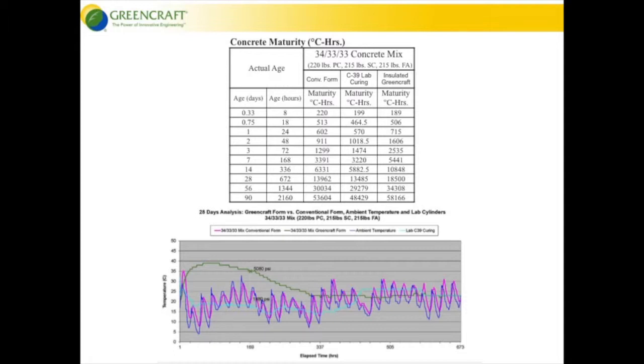Let alone stripping, reshoring, let alone the forms. Same thing, cored at 5 days, broken at 8 days: 1,400 PSI in a conventional form, 5,000 PSI in the insulated form. It takes about 45 days for that to get there in the cylinder lab, and somewhere around 60, 65 days probably for that strength to come up in the conventional form. That's why they call them what? The 60-day ultimate strength, when they specify these mixes, the 90-day strength, the Army Corps of Engineers.